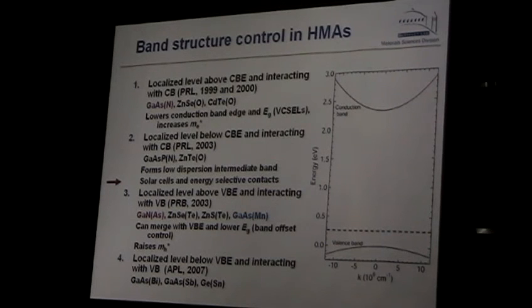Now we can do similar things with the valence band. What we have shown is that in this case we have gallium nitride with a little bit of arsenic, or zinc selenide with a little bit of tellurium. So we are substituting an electronegative element with a more metallic element. And we have a whole array of compounds we synthesized. In fact, there is an interesting case of gallium arsenide with manganese, which is not isoelectronic, but also has this level. And this is a famous spintronic material. There's a lot of work going on with this material, and we probably understand the properties of spintronic materials much better now because we know that it is also an anti-crossing interaction. Finally, we can have an element like bismuth or antimony in gallium arsenide. So we can manipulate the conduction bands separately and the valence bands separately or together.